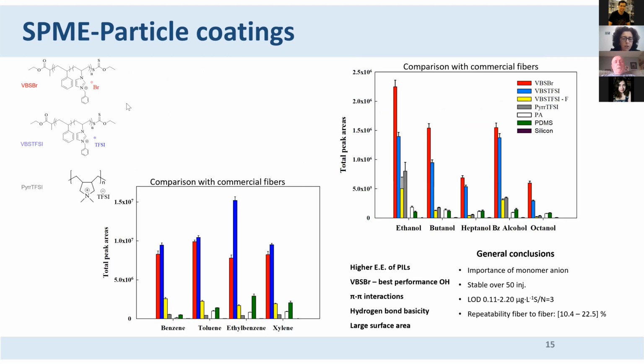Okay, so we used a complex sample to compare this particle coating fiber. First one with alcohols, and here we can see that we have an effect of the anion. So when we have polar compounds, it's the polymeric ionic liquid with the bromide counter anion that works really well. And here we have the 2 commercial fibers, the polyacrylic acid and polydimethylsiloxane. And we also did silicone just to make sure that silicone did not absorb.